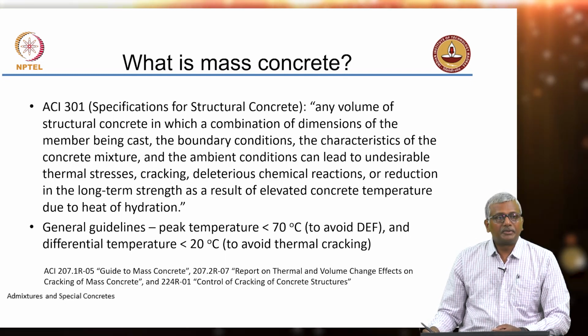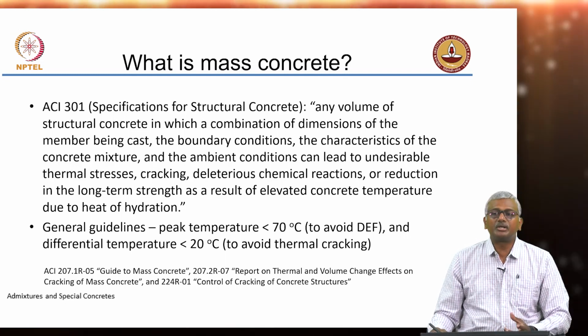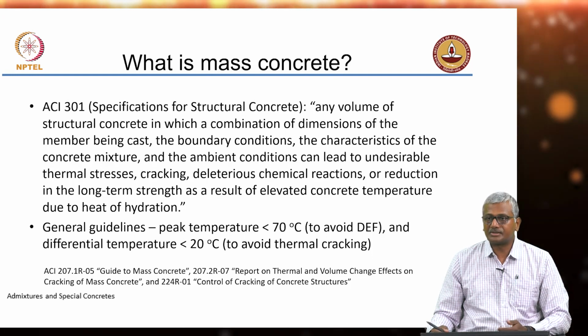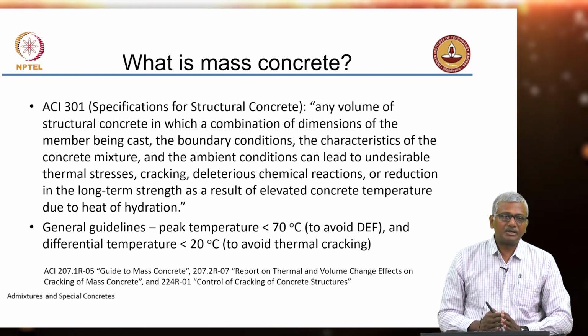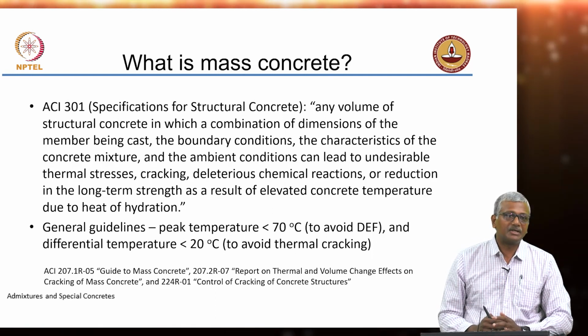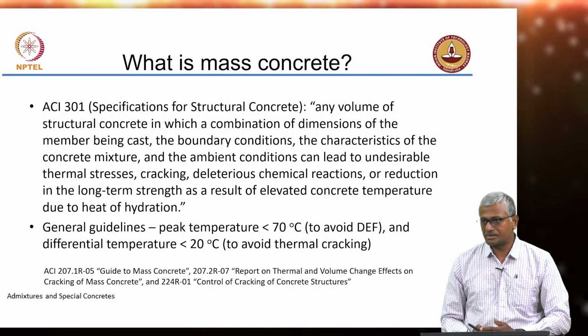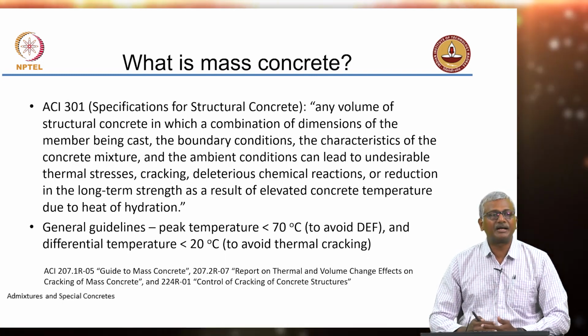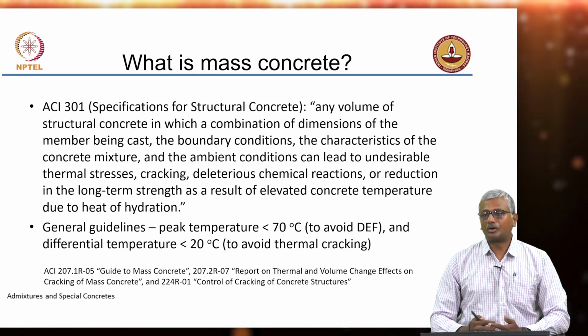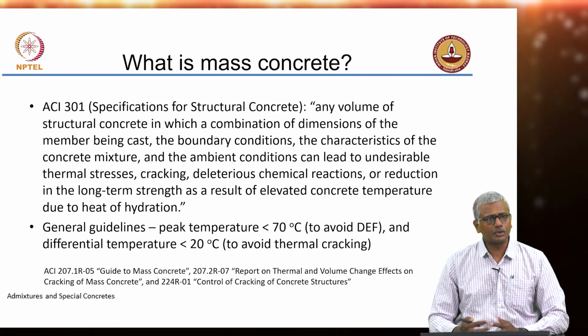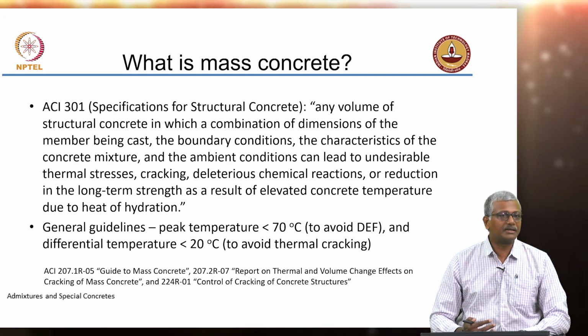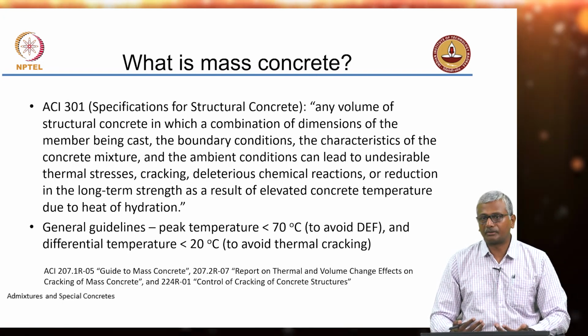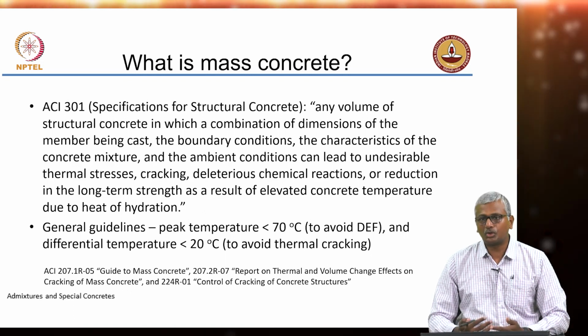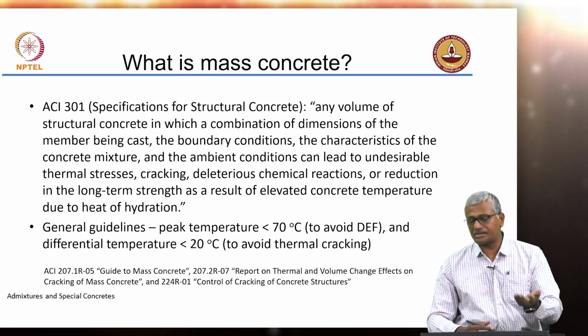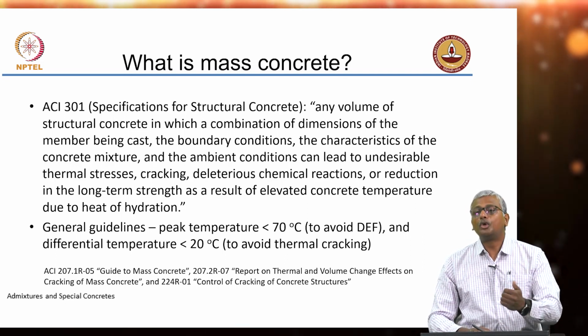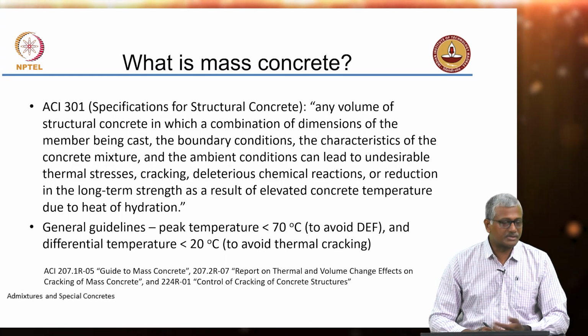And the other guideline typically followed in most construction projects is to keep the differential temperature down to less than 20 degrees Celsius. Differential implying between different segments of concrete, you keep the temperature difference below 20 degrees Celsius, because at that level you expect that the thermal stresses generated are not high enough to cause cracking. So, cracking will happen whenever the thermal stress is greater than the tensile strength of the concrete, right. So, in such an instance you need to ensure that the concrete has either a high tensile strength by the time the differentials are high, or low differentials to ensure that the tensile strength is never exceeded.